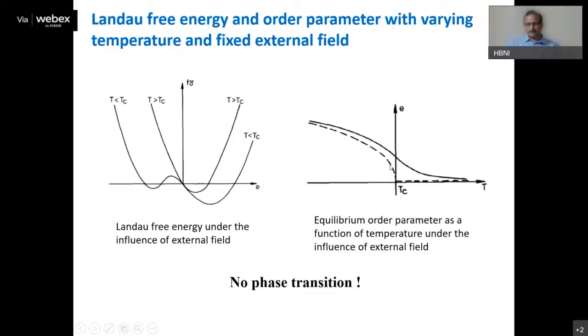The dotted lines are basically the behavior of the order parameter under no field. In this case, you can clearly see the order parameter was 0 up to a certain temperature and then increases. So this clearly shows the second order phase transition or continuous phase transition. Whereas as soon as you apply a field, even at temperatures very high compared to Tc, there is some value of this order parameter. And as you go across Tc, you see a continuous change in the order parameter, but this is not characteristic of any phase transition. You don't see any jump in the order parameter, nor the order parameter changing from 0 to some value.